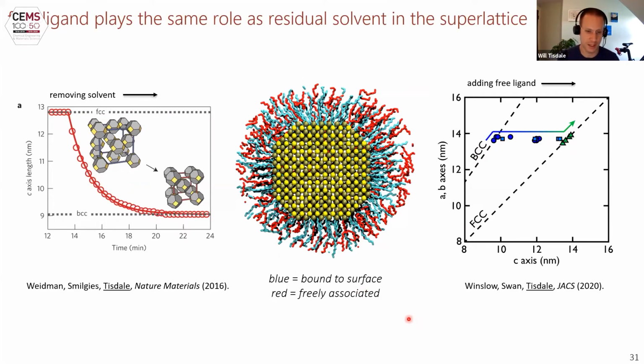This is a snapshot of a molecular dynamics simulation that Sam made. The blue are bound surface ligands and the red are free ligands. And you see in the MD simulation that the free ligand molecules associate themselves with the ligand shell, and that more free ligand can associate itself with the ligand shell when there's fewer ligands around the nanocrystal to begin with, up until a point, up until you completely saturate that surface and then additional ligand can't incorporate with the shell. And so the overall picture here is that the free ligand is playing the same role as solvent in the superlattice. It's effectively just a very low vapor pressure solvent that does not evaporate from the material as you evaporate your superlattice. So this was new understanding for us and new understanding for the field, to my knowledge.